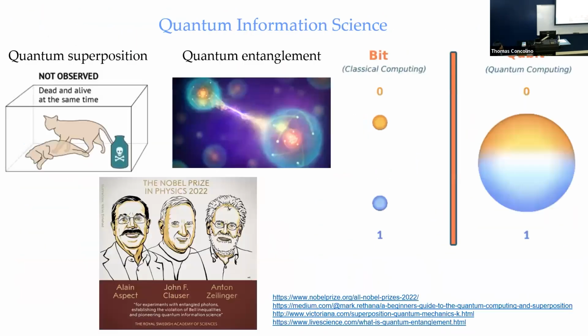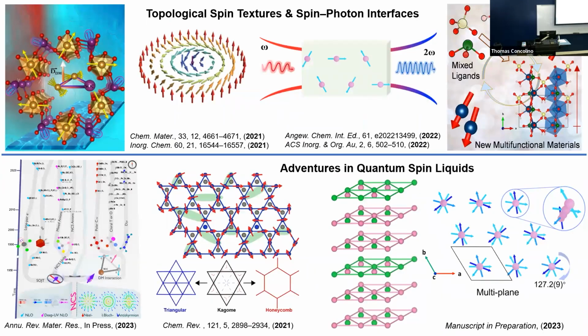Yeah, absolutely, thank you. Great point. I didn't present this work at all, but there's a way to do it. For example, you can couple a frustrated magnet in a triangular lattice or one-dimensional chain. Then for the optical response, if you excite the material with radiation, you can have a nonlinear optical response through second harmonic generation, which is the capability of generating coherent photons. The requirement for that is a structure that lacks inversion center symmetry, because when it lacks inversion symmetry, your second order susceptibility is different from zero. That gives you the signal.